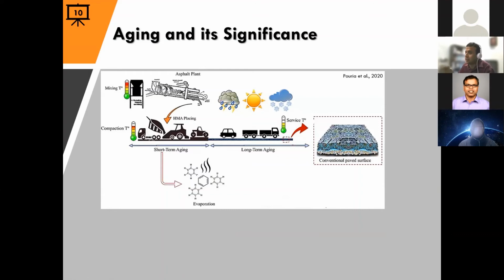In this project, we are talking about actually reducing the temperature. Warm mix actually means reducing the temperature, which basically means it will reduce your short-term aging temperature, which is reflected through the RTFO aging. And Dr. Hussein's last slide was a really nice lead into this presentation, because in this study, we do look at reduced RTFO temperatures and multiple cycles of PAV and everything.